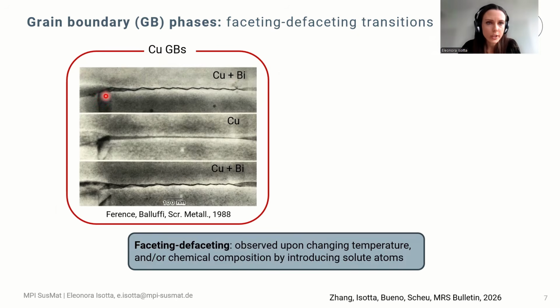This is work where faceting and defaceting transitions were characterized in copper grain boundaries. It was observed that when copper was alloyed with a little bit of bismuth, it was forming this faceted boundary. Then when the exact same boundary was annealed in vacuum to remove some of this bismuth, the morphology completely changed and became a planar interfacial morphology.